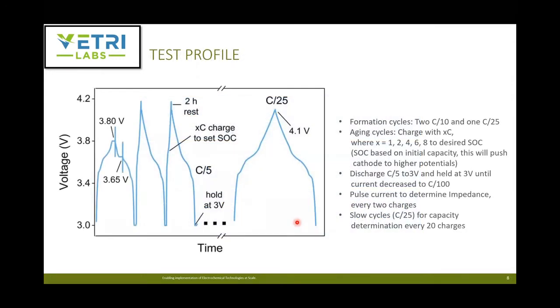Okay, here is the test profile that they followed. The initial formation cycles were at very low charge rates, C over 10 and C over 25, two of these cycles, and one C over 25. That's the initial cycles. And then the aging cycle is with XC, where the X ranged from 1, 2, 4, 6, and 8. That's this rise here. And then to the specific state of charge. So it ranged all the way from 30% to 80%.